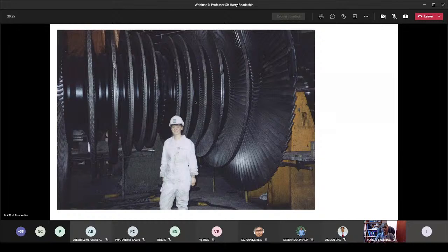And bainite can form at relatively slow cooling rates, which is why, for example, the steam rotor is made from 2¼ chrome 1-moly steel, which transforms through the section into a bainitic microstructure. So the advantage of bainite is that you do not need to rapidly cool, you don't set up stress gradients in your large component, and you get a relatively uniform microstructure in your whole component.